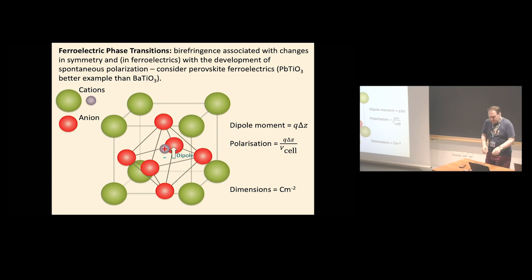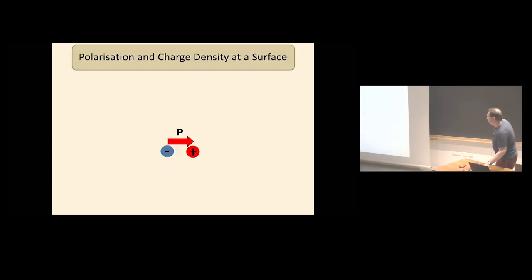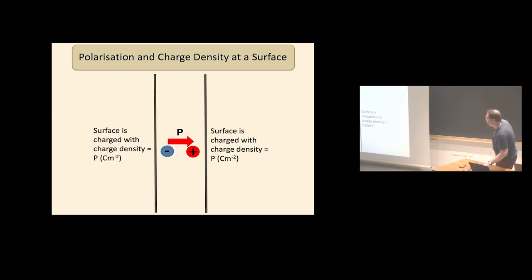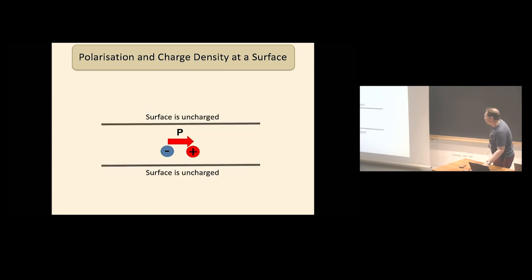And that gives away a little bit about how you would go about determining what the polarization value is. Typically you have a ferroelectric that looks like this with its polarization perpendicular to a surface, and you measure the bound charge that is accumulated on these two surfaces if it's a perfect insulating system. Okay, so polarization, charge per unit area, is manifest in the way in which one would measure the polarization, but you have to choose the right surface.